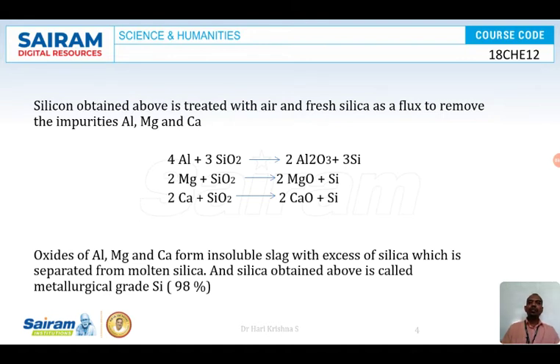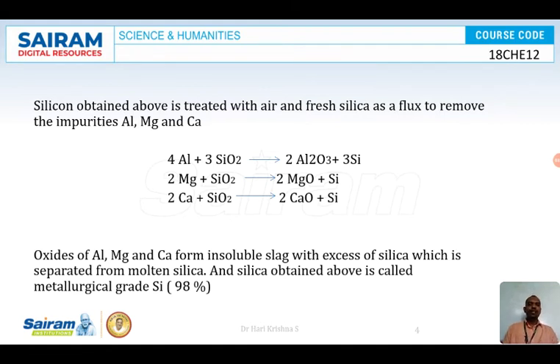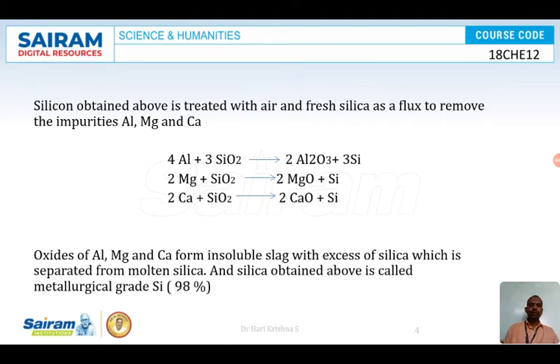To remove these impurities, silica is mixed with the liquid silicon and heated. If aluminum is present, it will get oxidized to alumina. If magnesium is present, it will get oxidized to magnesium oxide. If calcium is present, it will get oxidized to calcium oxide. It is not necessary that all three are present — any one or combination may be present and will be removed accordingly. The silicon thus obtained is called metallurgical grade silicon, which is 98% pure.